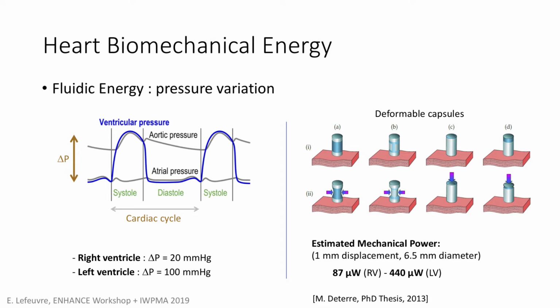You have here the blue curve, and you have a delta P, variation of pressure, which is a kind of quasi-static variation of pressure, and can be used to harvest energy, of course. In the right ventricle, the typical delta P is 20 millimeters of mercury, and in the left ventricle it's 5 times more. But our application is more in the right ventricle, so we have to deal with the smallest pressure variation. So how can we harvest the pressure variation?